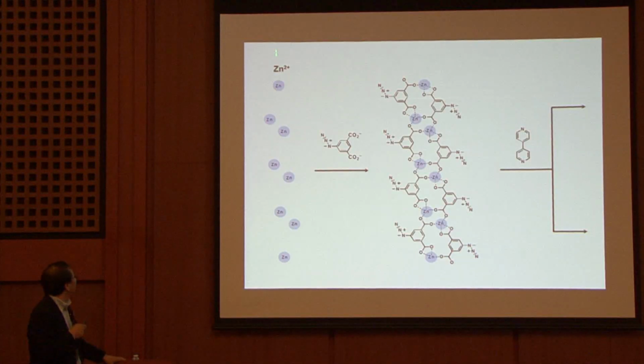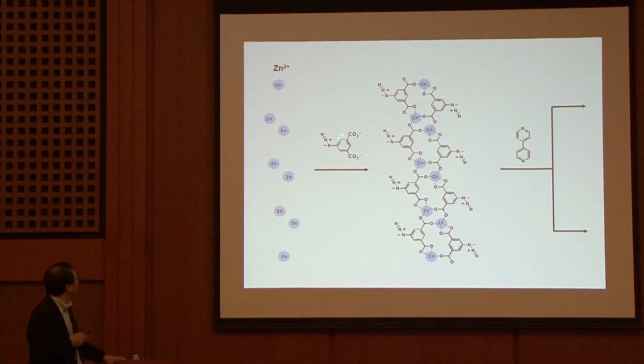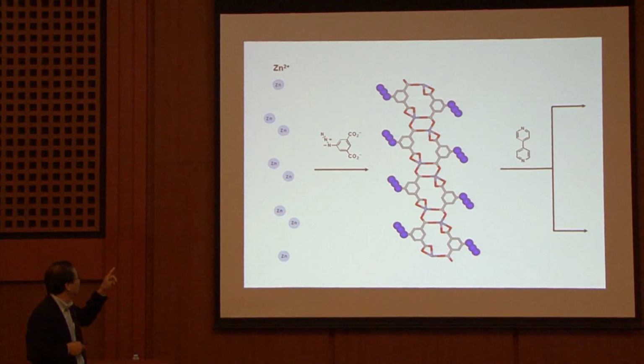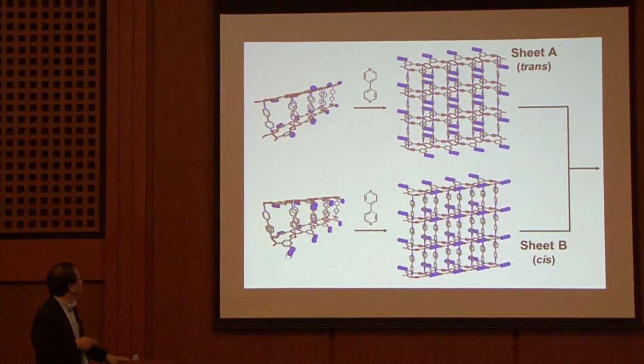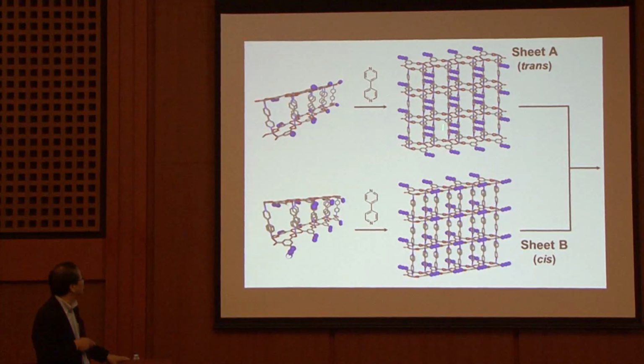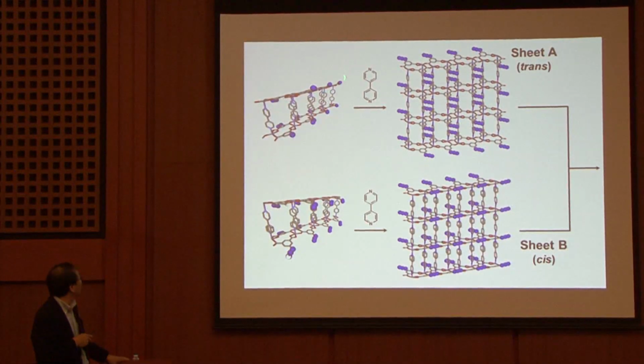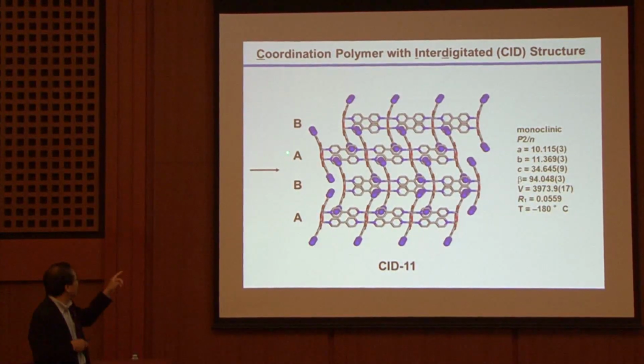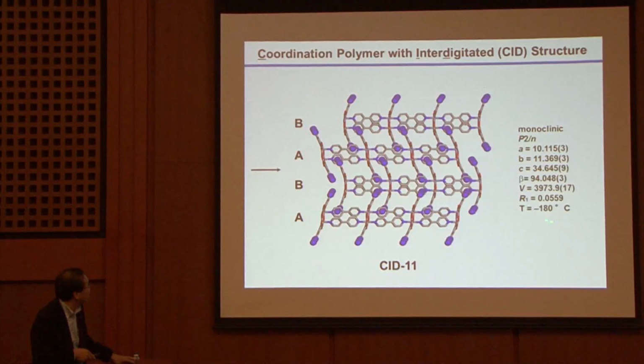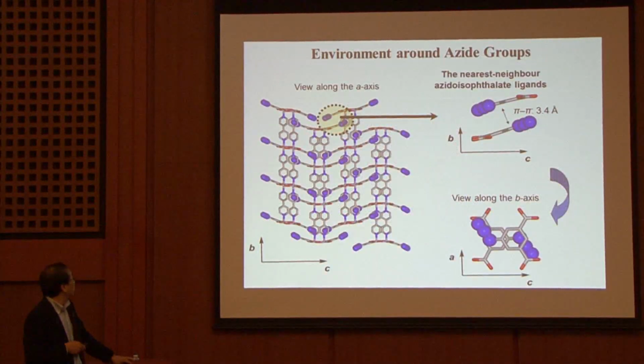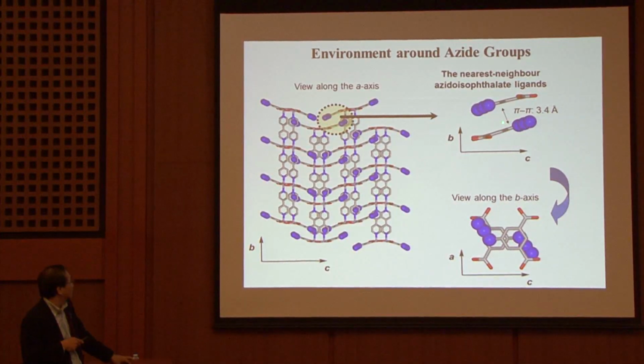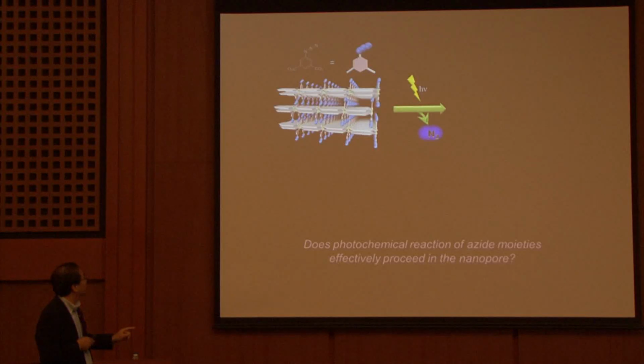The idea is that zinc is used for the framework, and the ligands are linked to give a layer here, two types of layers with respect to the direction of the azide group, and a stacked structure like this. This is just the crystal structure here. The relationship between the azide groups is like this. The distance is 3.4 angstrom. There is no strong interaction between them. That is very important. And then we irradiate this type of compound by UV light.